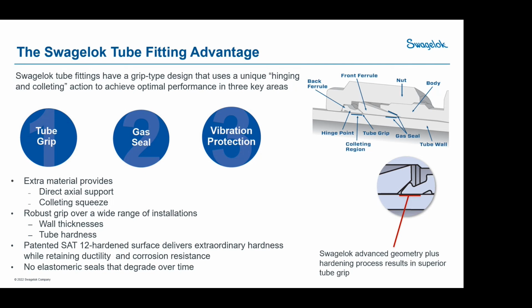Same thing happens along the tubing. It drives along the tubing and is able to go ahead and burnish that surface. So we get a very solid gas seal performance, metal to metal, right along both of those surfaces, that is able to hold back the hydrogen at acceptable leak rates throughout. The cool thing is that when you put this together, you pull it up a turn and a quarter, and it's done. It works every time.